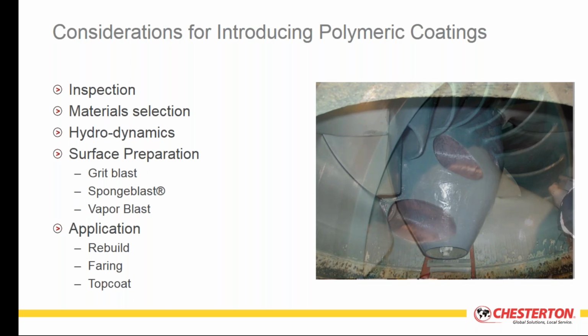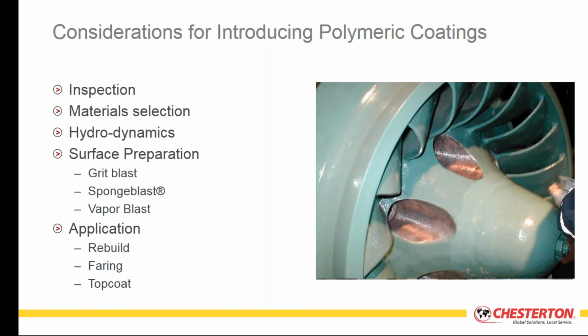We look at the coating systems as providing erosion resistance and corrosion resistance to pitting corrosion, galvanic corrosion, crevice corrosion, erosion corrosion, and cavitation. By protecting the weld regions where there's potential for stress corrosion, we can eliminate environmental effects that accelerate stress corrosion cracking.